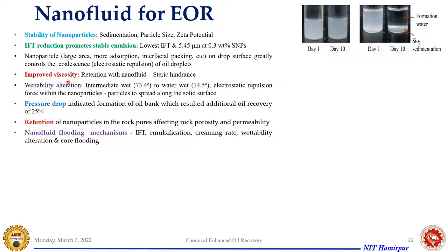So similarly, we have studied the improved viscosity pattern, like how the retention with nanoparticles was there. There is a steric hindrance kind of structure, a 3D macromolecular structure is formed, because of which the viscosity of the polymer or the aqueous phase is retained and will not get destroyed, and you will see a proper solid-like, block-like structure pushing the oil to the surface, forming a favorable mobility ratio. And as I told you, we were talking about this wettability alteration.